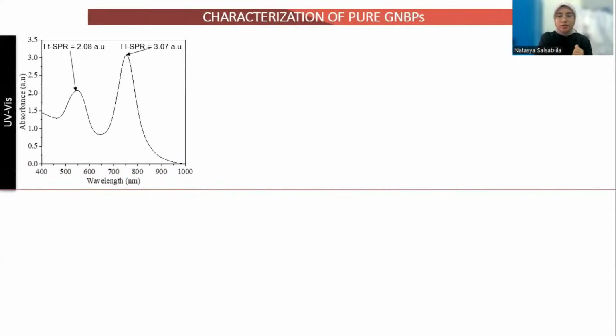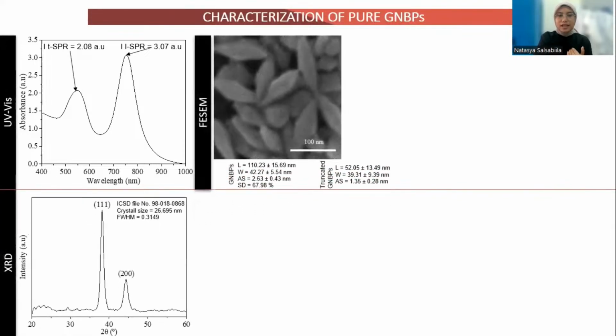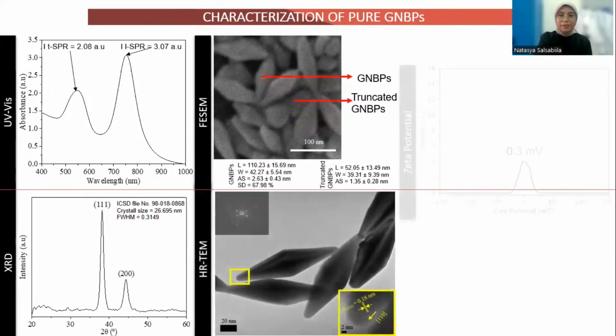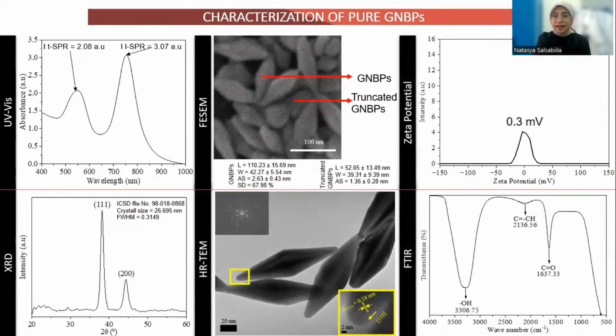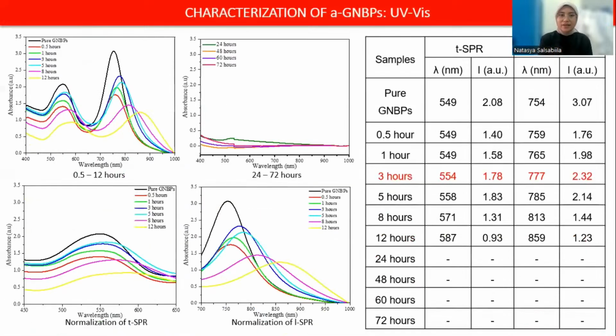Okay, this is the characterization result of pure GNBPs using UV-Vis, XRD, PSA, and then TEM, zeta potential, and the last one is FTIR to confirm that gold nanobipyramids or GNBPs have been successfully synthesized. Next, we move on to the AGNBPs. This is the UV-Vis results of AGNBPs or amine functionalized GNBPs. If you see here, in general, the spectrum shifted into the red region, indicating an increase in the aspect ratio. For your information, aspect ratio itself is the ratio between length and width of GNBPs.